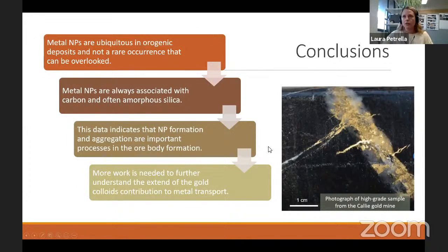In conclusion, our study clearly shows that metal colloids are not rare. It's quite the opposite. They're quite common in orogenic deposits. That tells us that processes associated with nucleation or aggregation of metal colloids are quite important to understand the formation of gold mineralization. We also show an association between metal nanoparticles and amorphous silica and carbon, and that can help us to understand better the behavior of these colloids. But we will also require more experimental work on this.